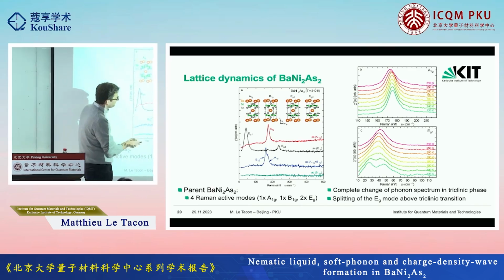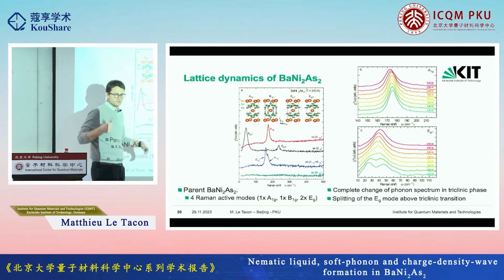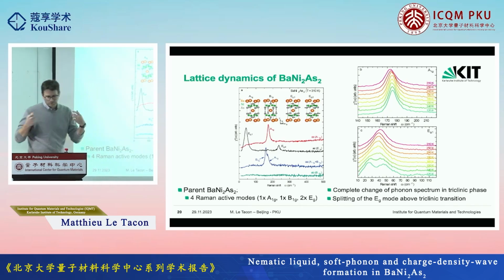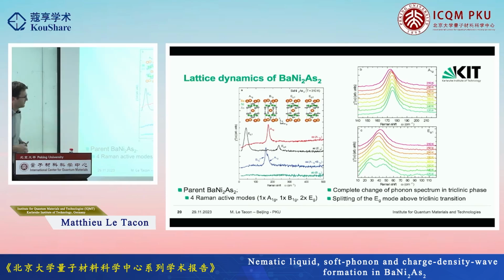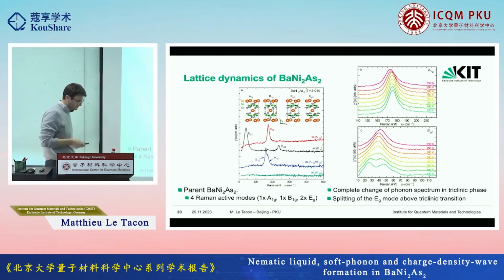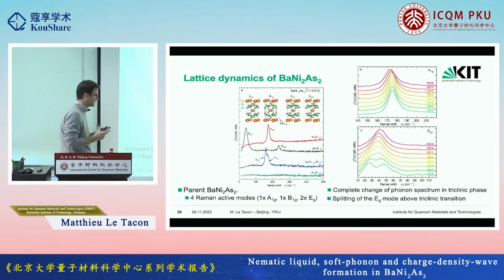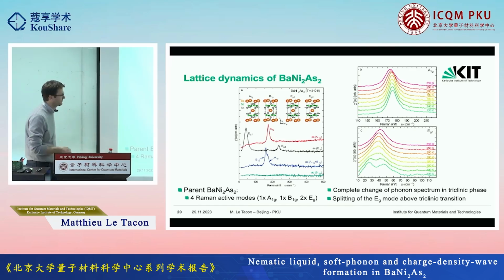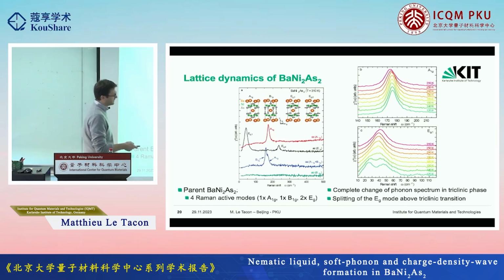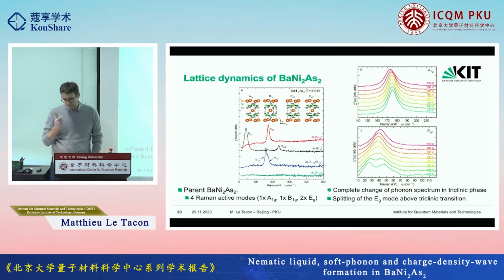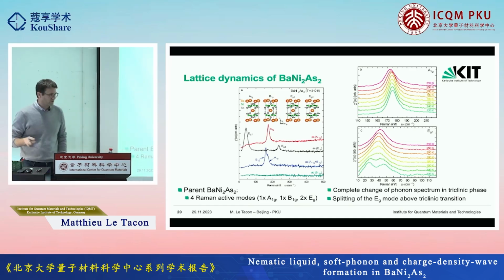First, it starts to soften, which is not normal when you compress a system, or when you cool a system down. Most of the time, when you contract the lattice, the phonon hardens, so it's kind of already a strange thing, and then it splits. So we were happy. We were looking for a signature of the splitting. We were looking for a signature of the orthorhombic phase, and there we have it. Wait a second.